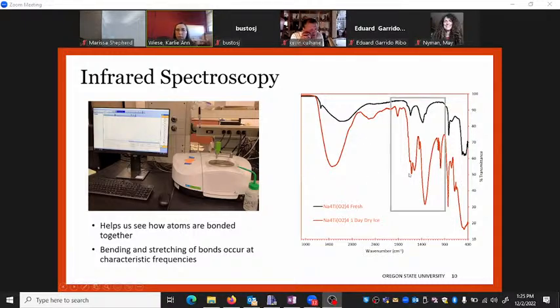This region in particular is of interest to us. We see there's some new peaks. The intensity of the peaks is getting a lot stronger, and so something's changing within the structure. In particular, this is a region where we would see carbon-oxygen bonds from CO2. And so it makes sense that we would see that there. So that's a good confirmation.